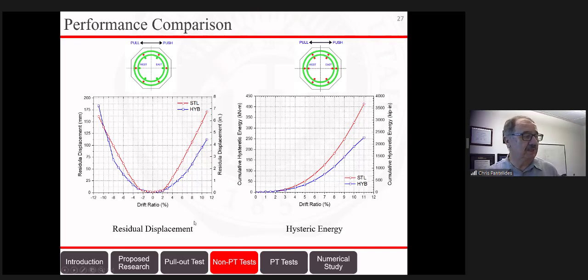So these two specimens were pretty similar up to the design drift ratio of 3%. And after that, the steel column, the red, dissipates much more energy, of course, as is shown here. So this is the compromise. You can see in these two curves, if you want to dissipate more energy, you can use the all steel column. And if you want to minimize the residual displacement, you should be using the hybrid column. So of course, this now shows you why we also try to do the test with the post-tension columns, because we wanted to investigate how much better we can make this residual displacement, which is already pretty good.